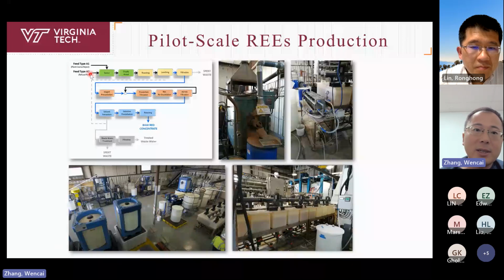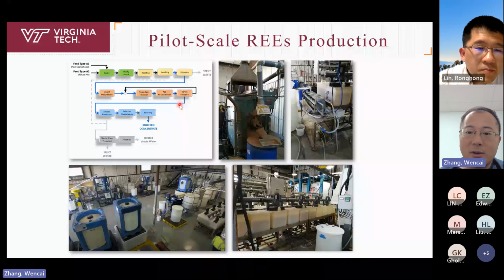As you can see, a lot of technologies I introduced, I employed in this plant. For example, in this circuit you have roasting, and this is a roaster we used in the pilot plant. You also have stage precipitation, as these tanks are used for the stage precipitation. After stage precipitation, you can directly go to oxalic acid precipitation. What you can do is solvent extraction. So this is a solvent extraction line. And after that, you can do oxalic acid precipitation to get your product.